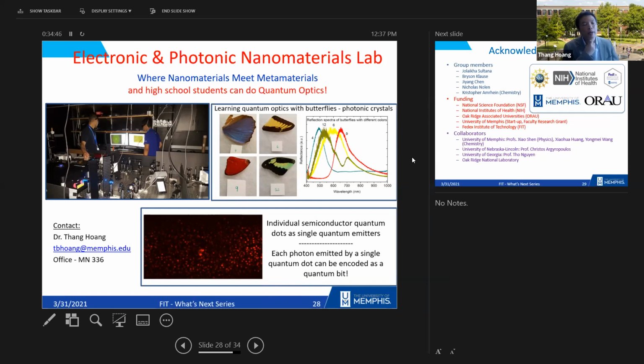Yeah, certainly. Actually, the plasmonic has two consequences. One is the thing that I showed there, they enhance the properties of nanomaterials. But on the dark side, the plasmonic nanoparticle quenches. If you have a nanoparticle with a very sharp tip touching directly your 2D material, then a quenching effect happens. Let's say you generate an exciton, an electron and hole pair, in your 2D material, and then that electron hole pair is going to be captured by the metallic particle. So in that case, you get a quenching effect, which is an unwanted effect.